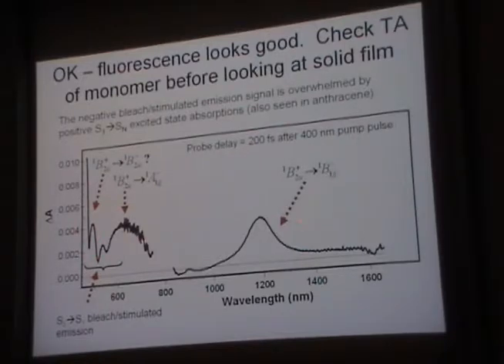And we can sort of tentatively identify these induced absorptions. The excited states of tetracene are pretty well known. One thing I would point out is, so first of all, the bleach is there, but it's tiny. It's swamped by the induced absorption from the singlet state. So that means things are going to be complicated.